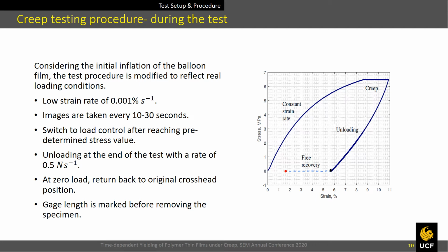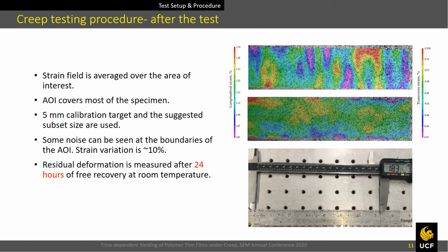back to original position. The strain field is averaged over the area of interest, which covers most of the specimen. On the right, some sample strain contours can be seen: longitudinal strain at the top and transverse strain at the bottom. Some noise can be seen at the boundaries of area of interest. The residual deformation of the gauge length is measured by caliper after 24 hours of free recovery at room temperature.